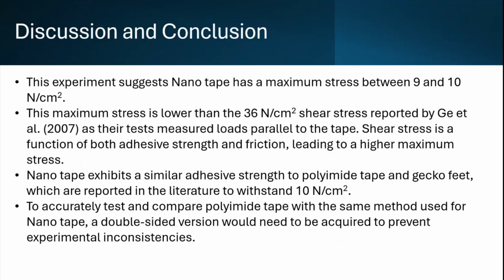All right, the discussion and conclusion. This experiment suggests that nanotape has a maximum stress between 9 and 10 newtons per centimeter squared. The maximum stress is definitely lower than the 36 newton per centimeter shear stress reported by Ge et al., but this makes sense because the shear stress also takes into account friction as they are pulling the tape parallel instead of pulling it perpendicular.